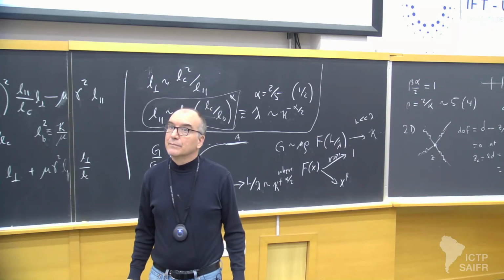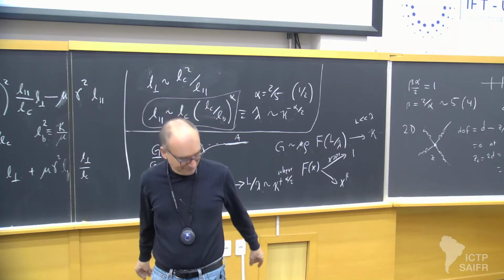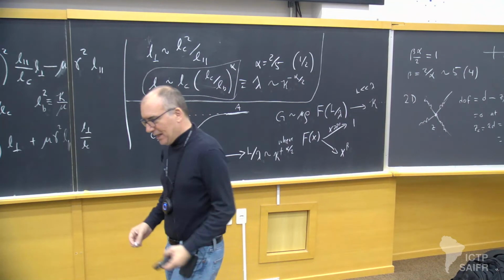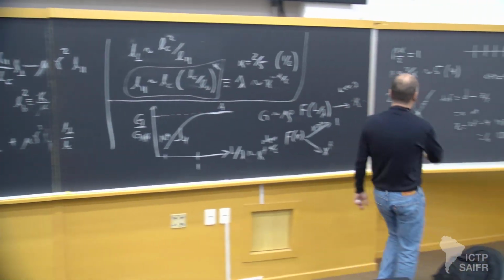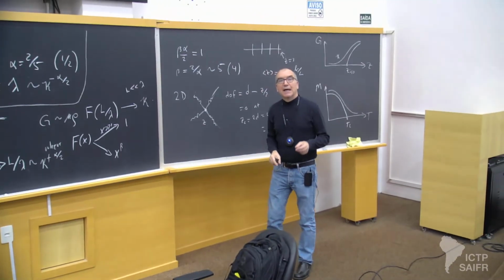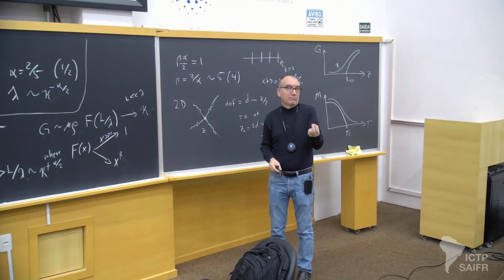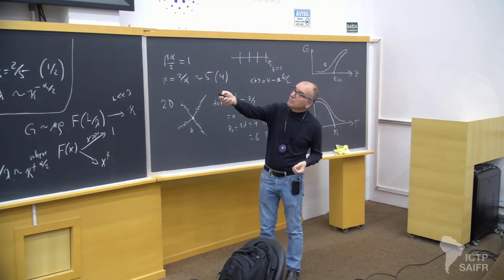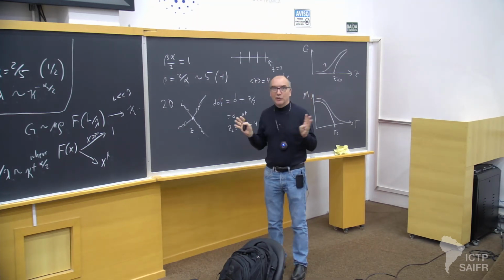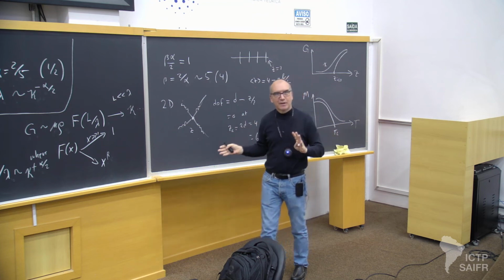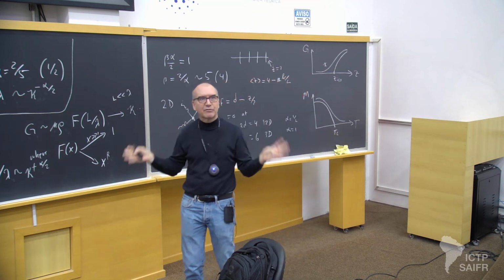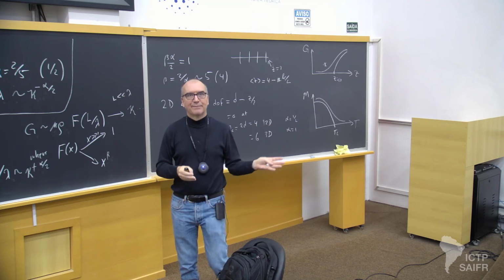Yeah, sorry. So that's a separate. Yeah, so if I add bending energies to the Maxwell picture, I change the way I count constraints. I get stable networks, possibly at a lower modulus, by the way. By the way, the Maxwell argument only says 0, non-zero. It doesn't say anything about the magnitude of the modulus. If it's non-zero, it's rigid. If it's 0, it's floppy.